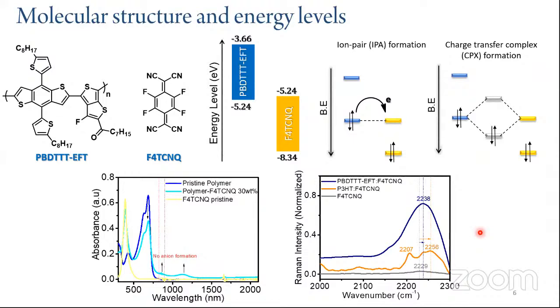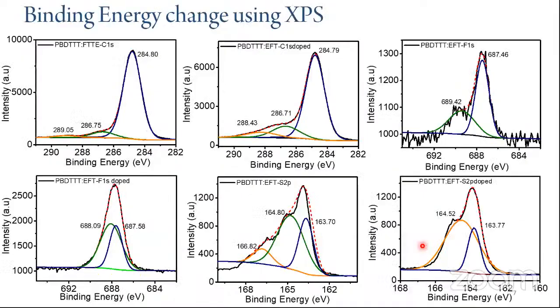Further, the Raman spectrum of the pristine sample is compared with that of a known polymer, that is P3HT, which is known to dope with ion pair formation. We can see that the Raman shift of the C triple bond N is much higher in the case of P3HT than in the case of our polymer, where a formal charge of less than 1 electron is transferred. So in that case also, we assume that our mechanism of charge transfer is via the CPX formation.